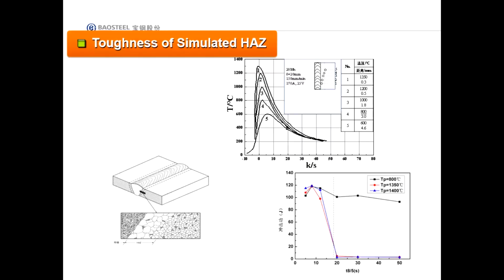Second, the impact toughness of simulated HAZ at the interested position can be obtained. In this test, the square sample is required. This is the example we did. And the test uses different peak temperatures and different cooling rates.